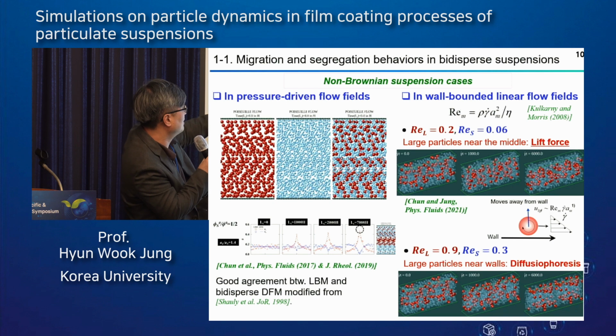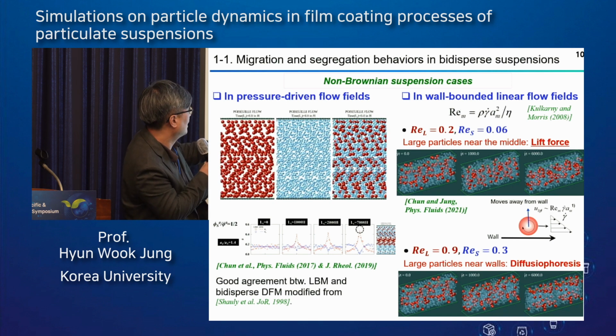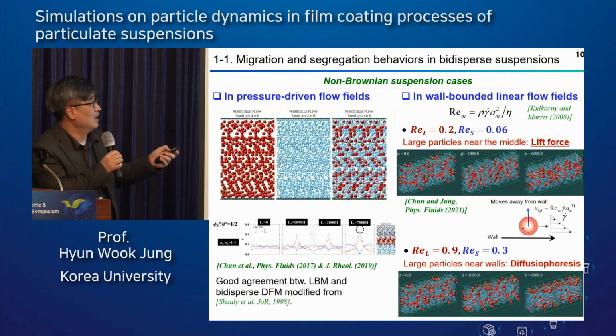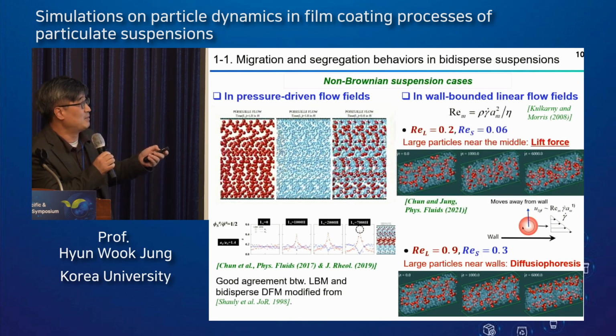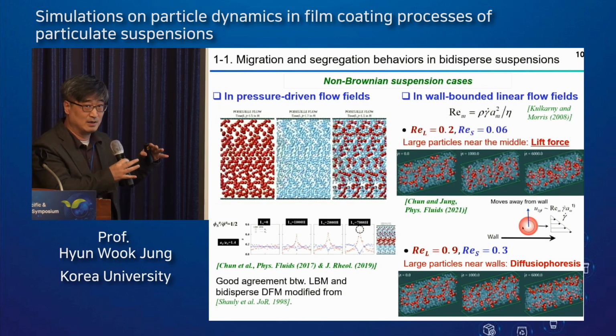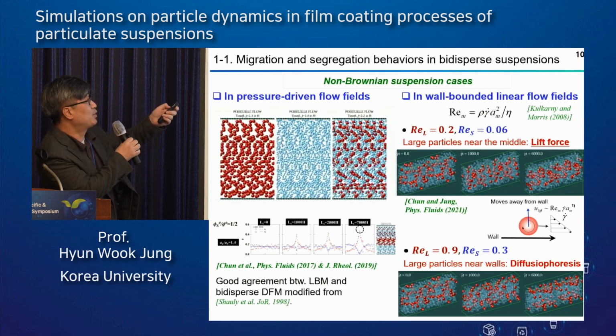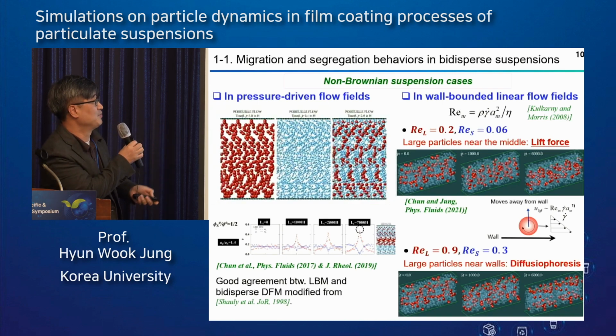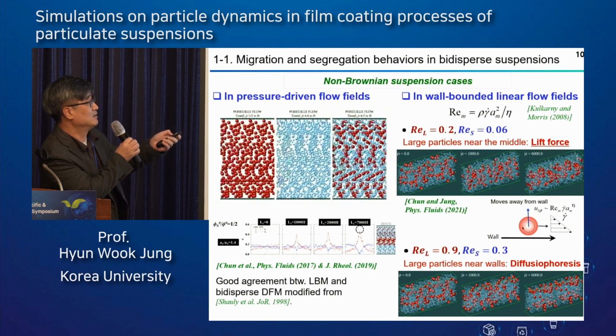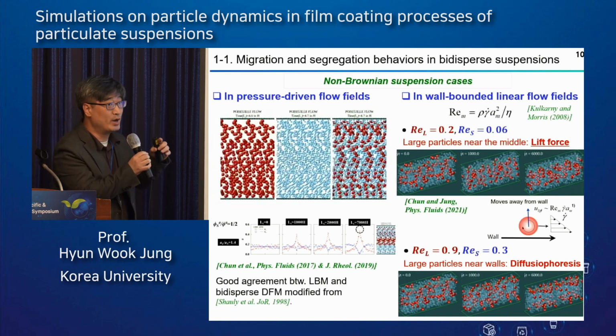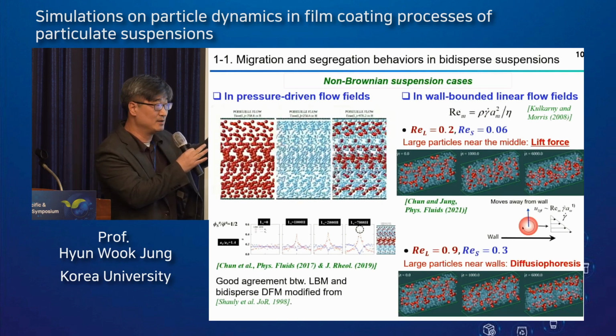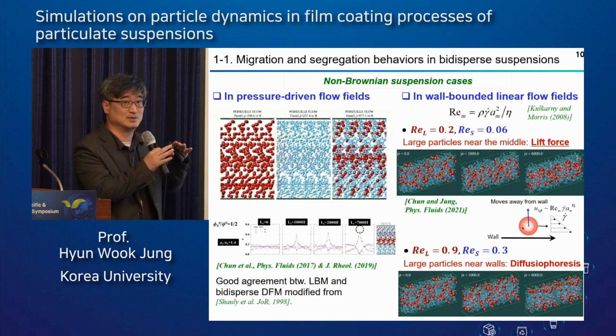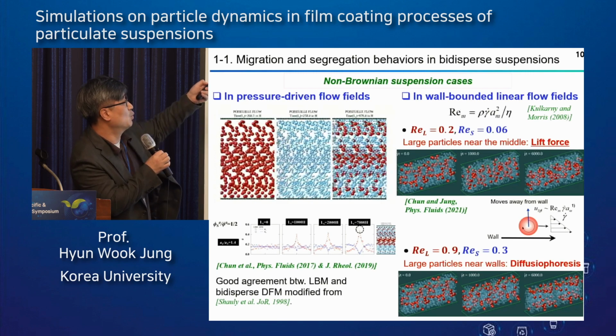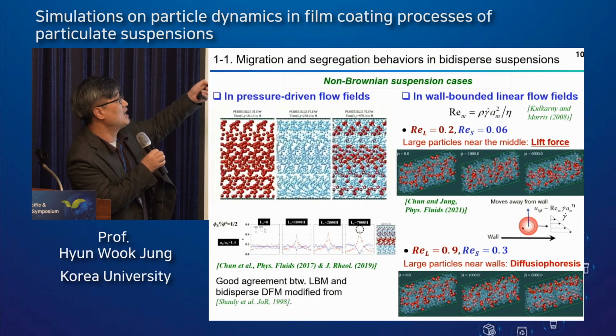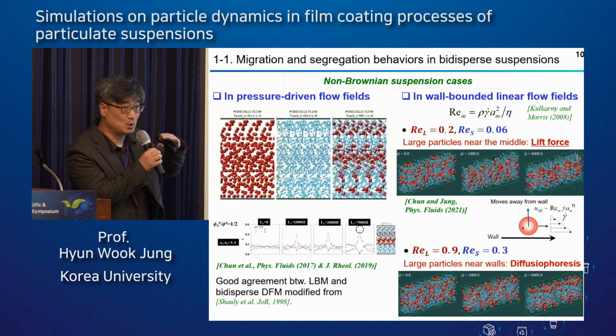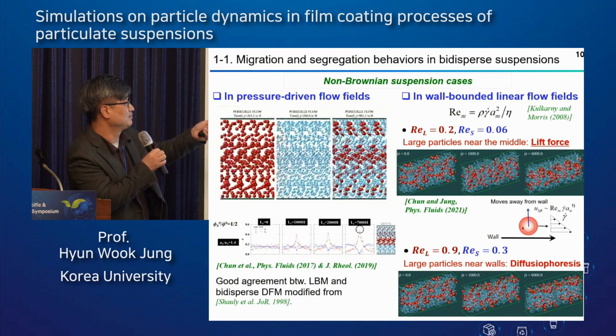Let's see the left movie. You can see monodispersed particles and bidispersed particles moving within the slit channel under the pressure-driven flow field, as shown here. In that case, the monodispersed particles, in both cases, will migrate toward the mid-plane due to the shear-induced migration. So particles will move from the wall to the center, from the high shear rate regime to the low shear rate regime, as shown here.